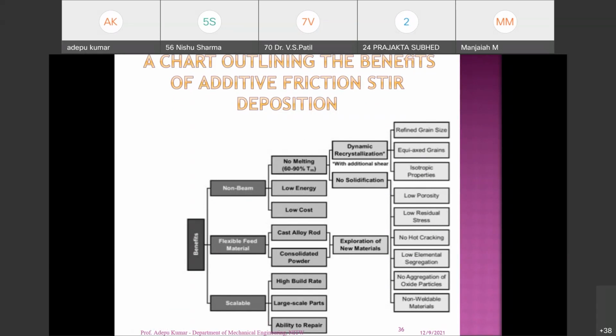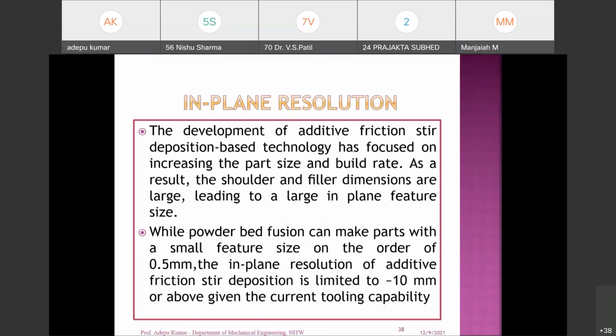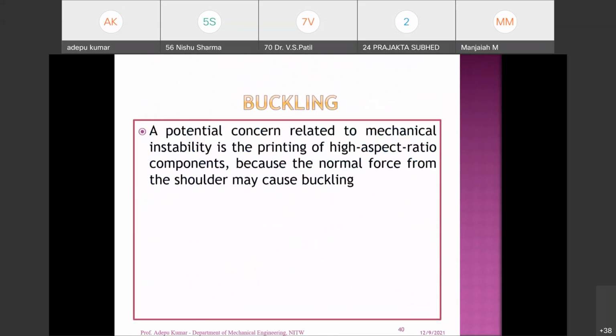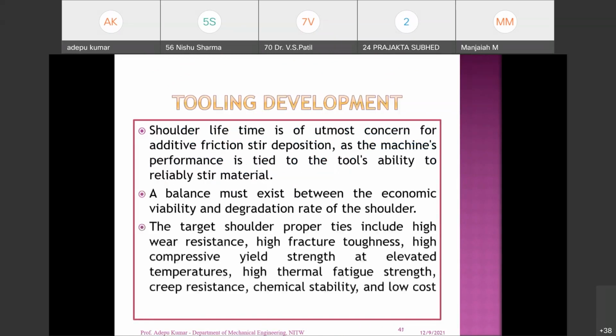So, the limitations: mainly the buckling issue when you are going up to a certain height. Beyond that, buckling is a problem because you are always applying downward force. Without force, you cannot build the component because we need friction. For that, you need a sufficient amount of downward force and firm contact. That's why buckling is a major issue in this case.